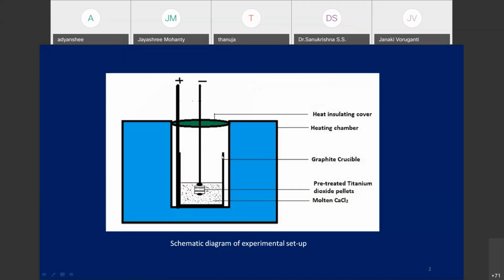Then the electrolysis is carried out, and during the electrolysis, the oxygen goes into the solution, and the calcium is there to capture the oxygen to produce calcium oxide. The potential is sufficient to decompose the calcium oxide into calcium and oxygen again, and the oxygen goes to the anode material like carbon or graphite, where it reacts with the carbon to produce CO or CO2 at a temperature of 900 to 950 degrees centigrade. So this is the mechanism of preparation of the metals from the metal oxides.